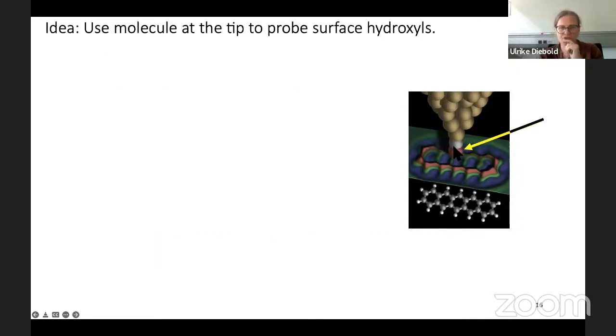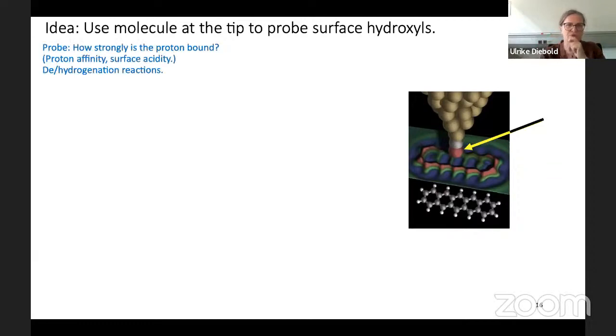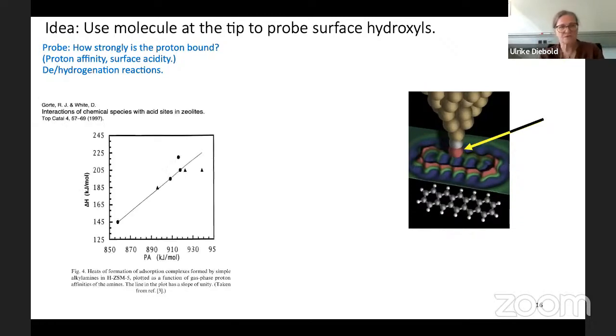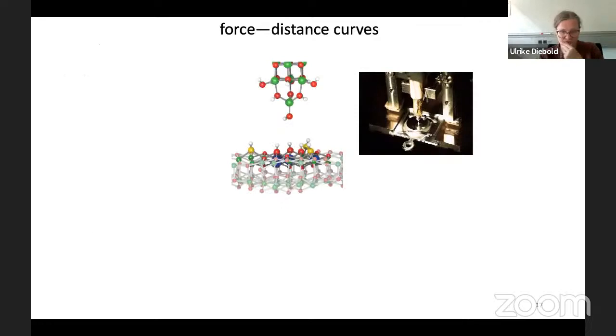So what we want to do now is probe these hydroxyls on surfaces by having this tip functionalized. So the tip is our probe for how strongly this proton is adsorbed on the surface, right? With atomic resolution. That's what we want to do. So how strongly is a proton bound, which has to do with proton affinity, surface acidity and surface hydrogenation reactions.